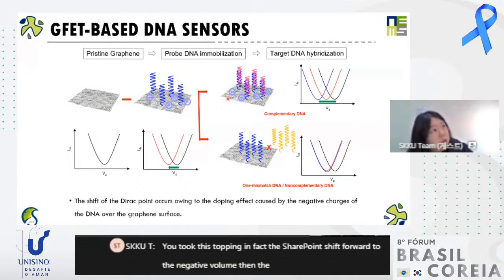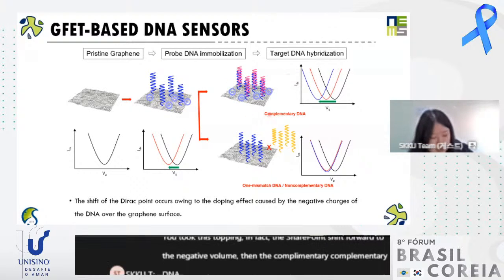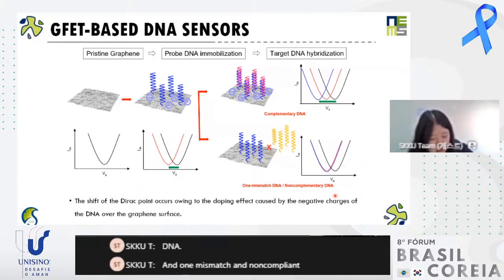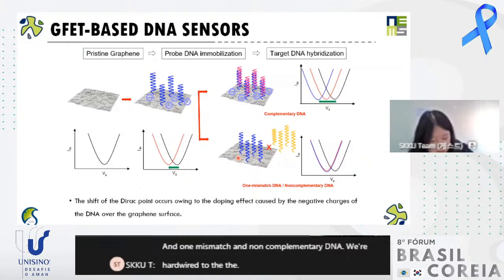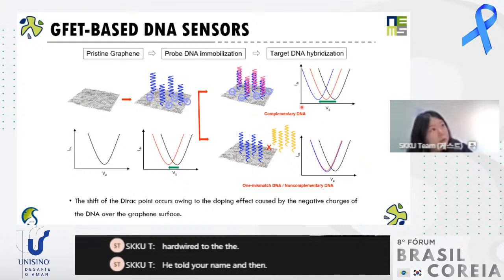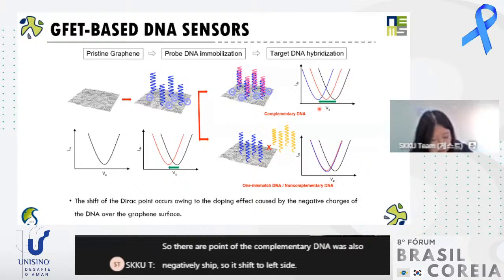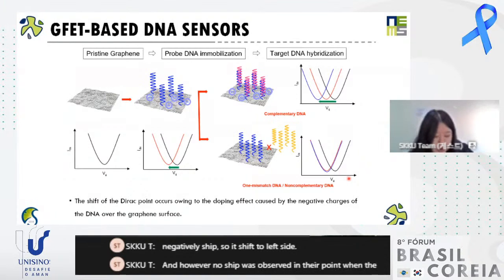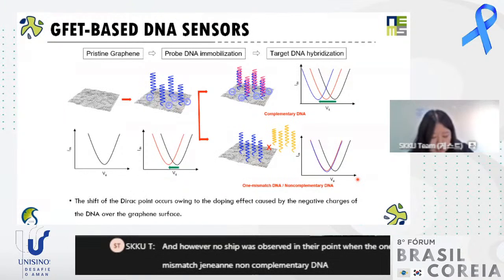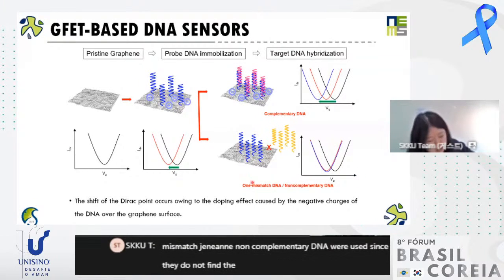Then the complementary DNA, one-mismatch DNA, and non-complementary DNA were hybridized to the probe DNA. Due to the negative charge of the DNA, the Dirac point of the complementary DNA was also negatively shifted, so it shifted to the left side. However, no shift was observed in the Dirac point when the one-mismatched DNA and non-complementary DNA were used, since they do not bind to the probe DNA.